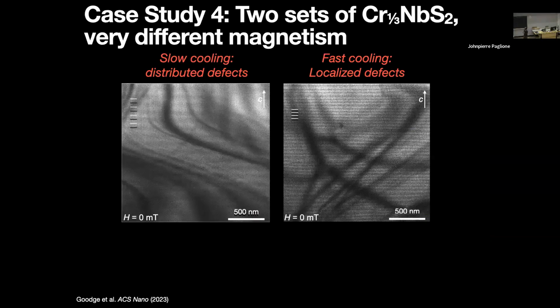What we found quite surprising when we were looking at that helimagnetic system that I talked about is we had 2 sets of growths, one which we call slow cooling, about 20 degrees per hour, and the other which we call fast cooling, which is about 60 degrees per hour. And what we found is that these were compositionally, stoichiometrically identical within our ability to resolve that by elemental analysis.